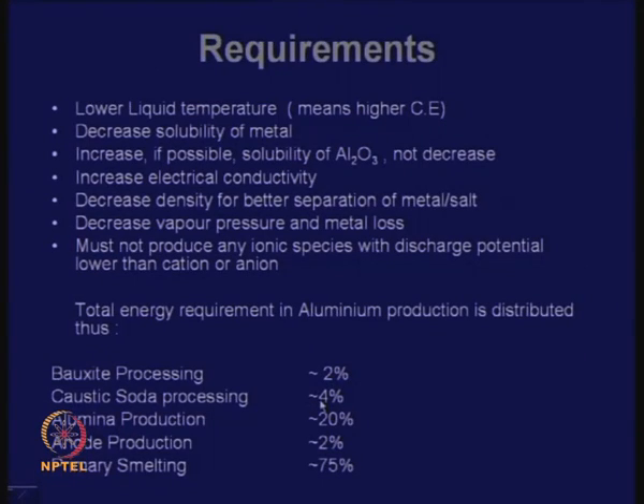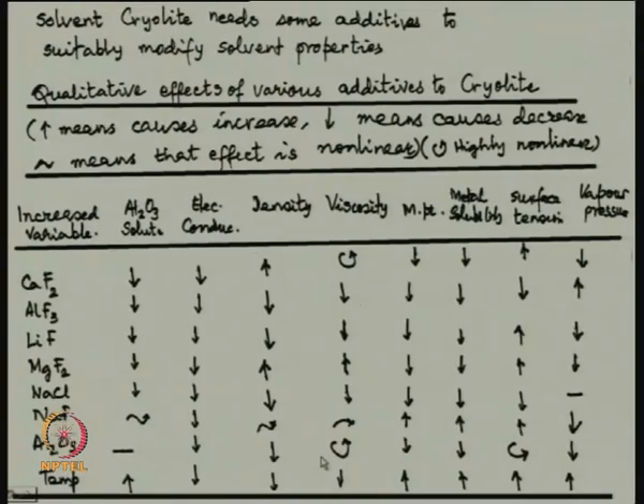Before I go deeper into it, just let me give you an idea about where energy is going in the aluminum industry. I have been mentioning that it is very energy intensive. 2% of energy goes in bauxite processing, caustic soda processing 4%, alumina production about 20%, because it needs grinding, autoclaving, all kinds of pumping. Anode preparation, we have to make graphite anodes, but maximum 75% is going into primary smelting, meaning the electrolytic process. That is where maximum energy is consumed.